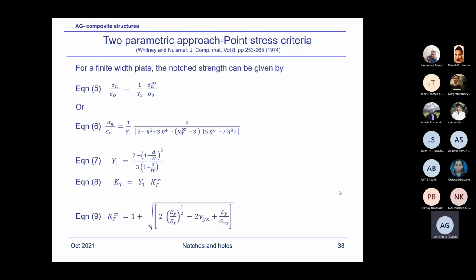Under fatigue, fatigue is very complex, and you can't predict the behavior. In composites, normally we use the no-growth phenomenon. In metals, we use the growth because you can predict the crack growth by da/dN equal to C delta K^n, the Paris law. In composites, except for delamination, there's no way you can easily predict through-thickness crack damage propagation. A lot of work has been done, but there's no method available which can predict the fatigue behavior. And that's why in composites, we do not use damage propagation at all in fatigue. We design it based on no propagation, no damage growth. That is the criterion in composites, which I talked about in my certification.